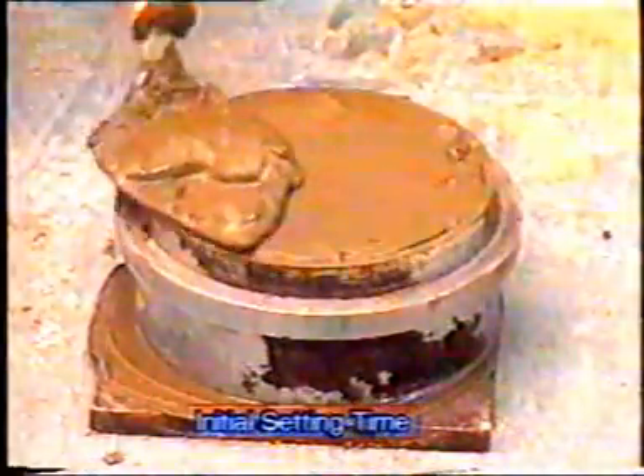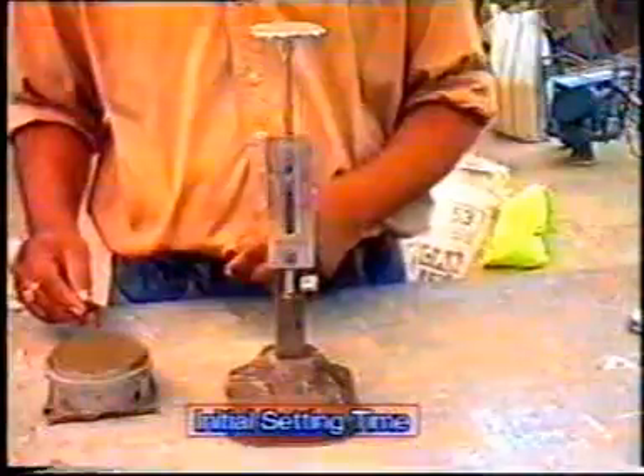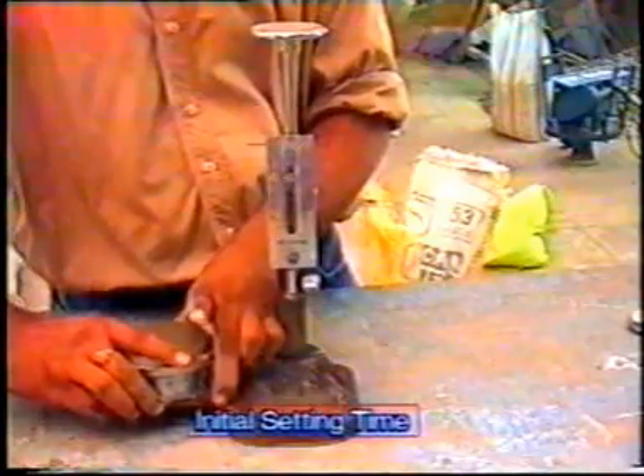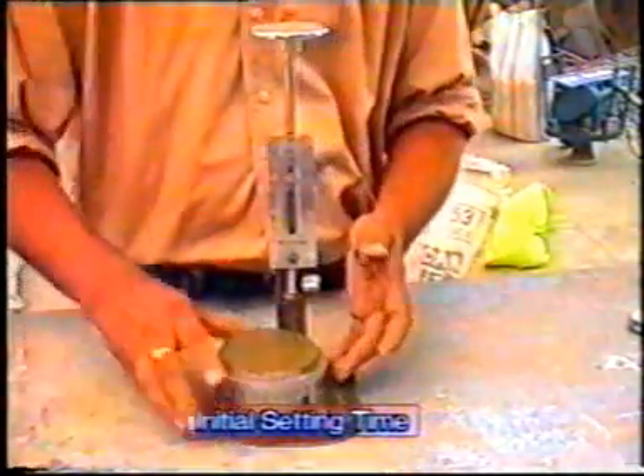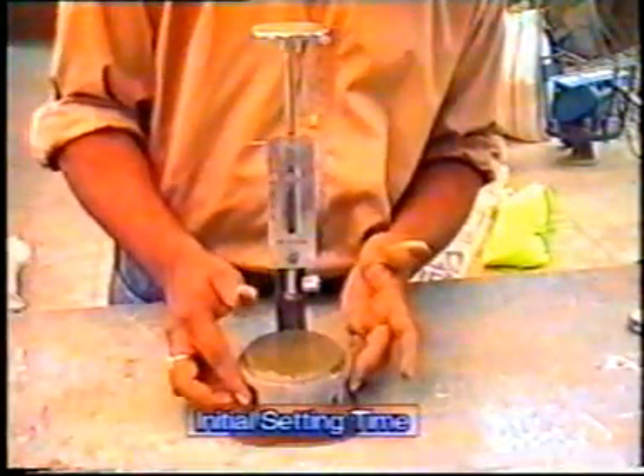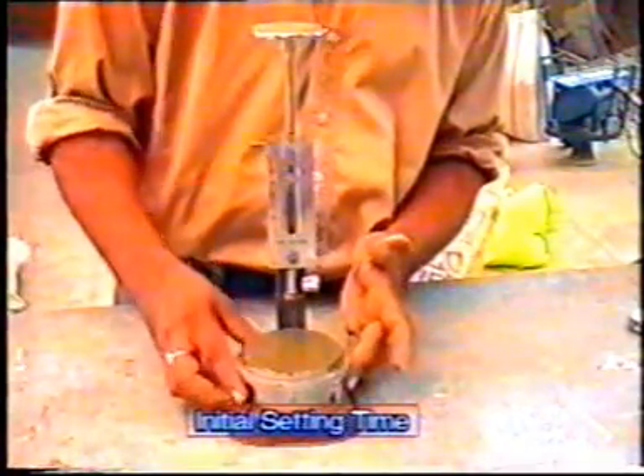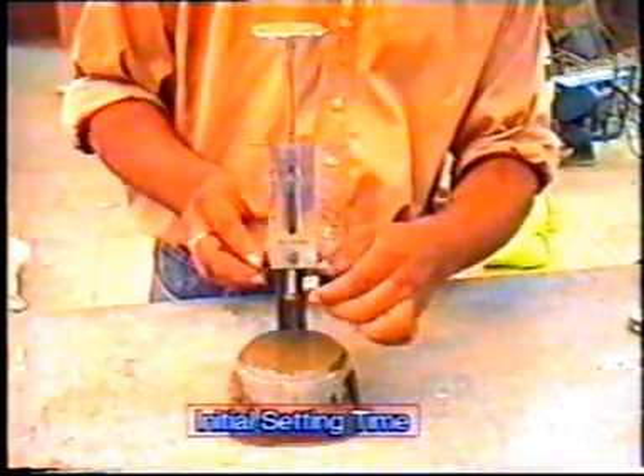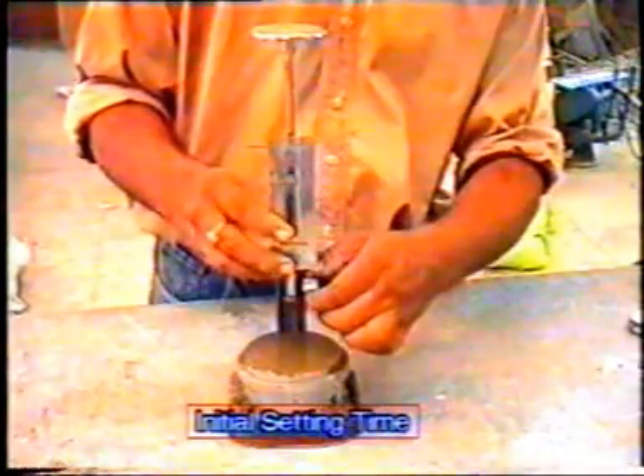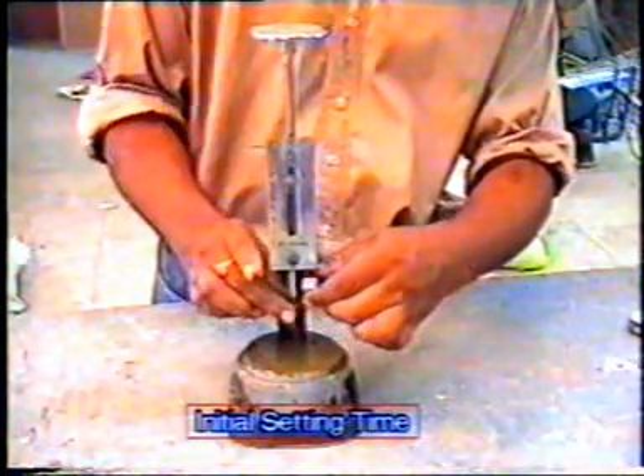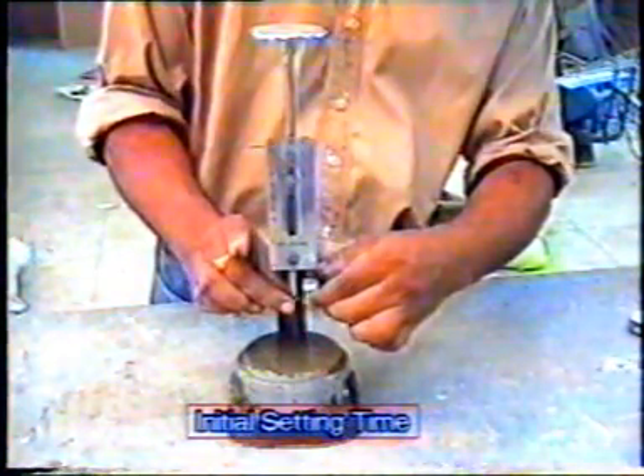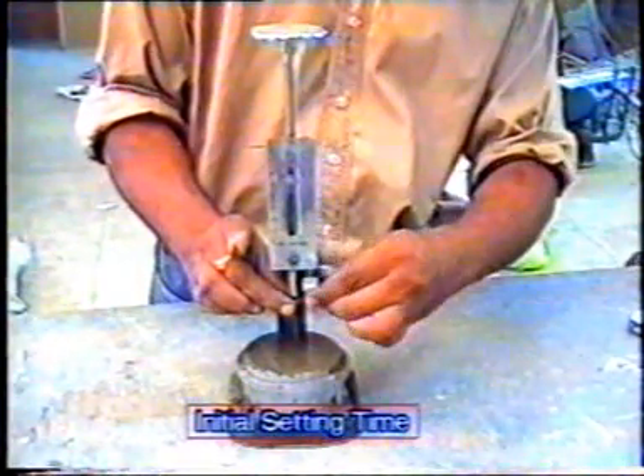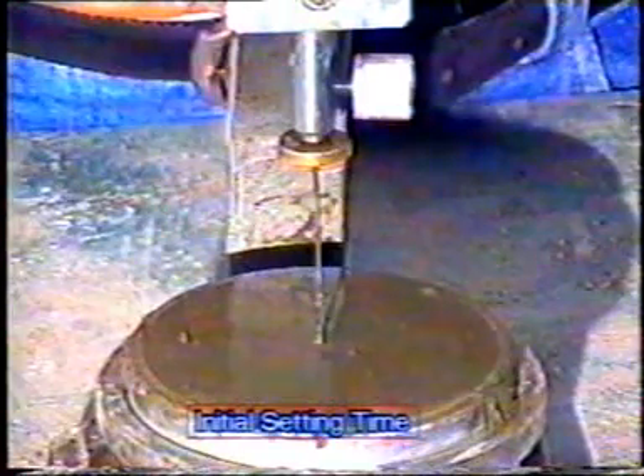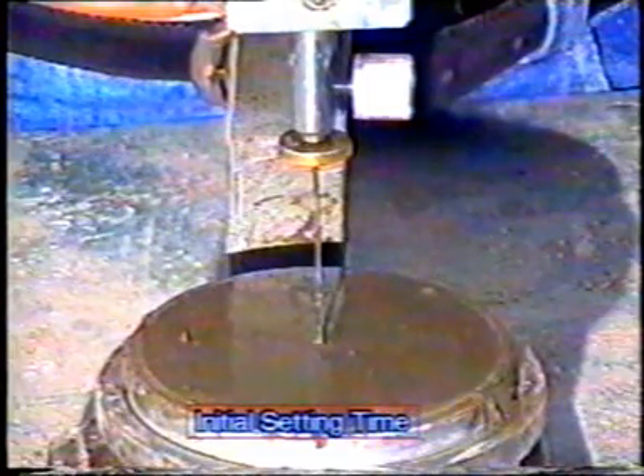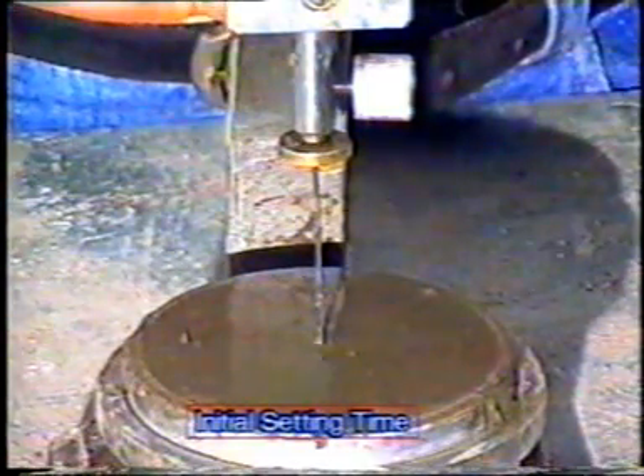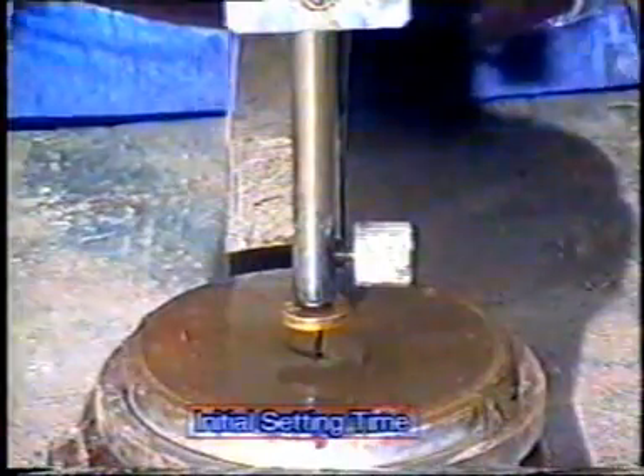Level off the surface and place the mold under the Vicat apparatus needle. Lower the needle gently in contact with the surface of the test block. Quickly release the needle to penetrate into the test block.